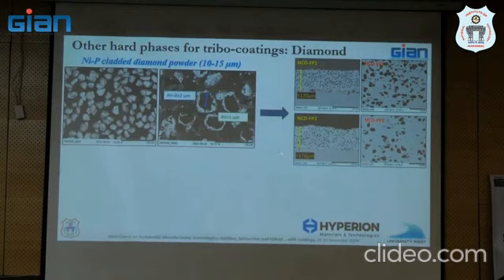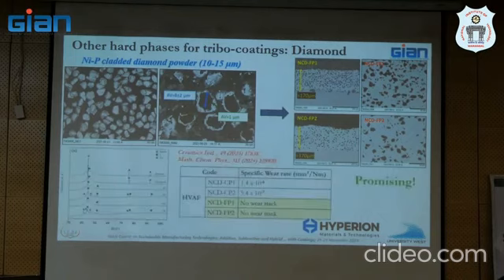Two things happened. One is we lost a lot of diamond. We could retain only 15% of the diamond. The second thing was all the diamond which was retained was much finer than what we started with. So there was fragmentation of diamond. Those are still problems, but we found outstanding wear properties. We couldn't even see a wear track when we did the wear test. It was that good. So we find this extremely promising. That has been the subject of a couple of our recent papers on thermally sprayed nickel-clad diamond.